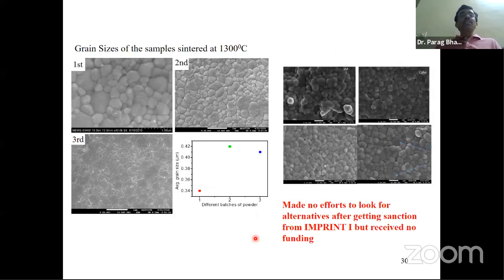Okay. So these are the pictures. I have not shown you powder pictures, but let me tell you, we are now able to make powder almost as good as Tosoh. And you can see this is the picture of our sintered material from our powder, and this white line is 1 micrometer. So our grain sizes are smaller than 1 micron. Then you can imagine hardness and strength goes up, and we almost achieve the same kind of microstructure as we get with commercial powders. This is what is obtained from Tosoh kind of powders. So it's a beautiful material.